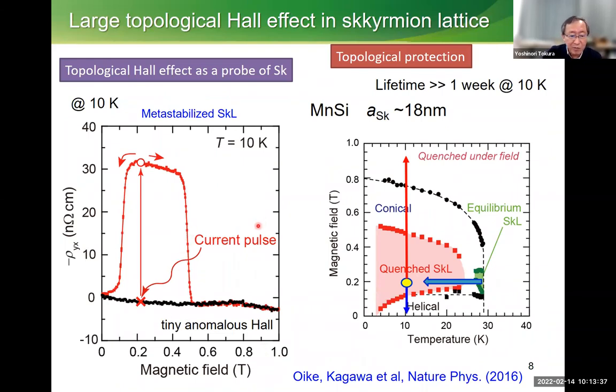Let me show some examples. This is a manganese silicide compound, and we measure the Hall effect as a function of the magnetic field. At low temperatures, although there is a fairly large anomalous Hall effect, in terms of the Hall resistivity it's a rather small one. But the skyrmion phase is in the plane of magnetic field and temperature, we have this kind of small pocket region. Skyrmion is only present in very small windows, but the skyrmion is protected by the topology.